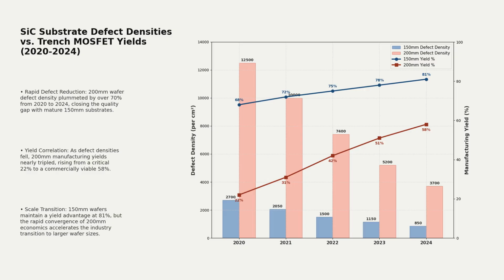These defects, primarily threading screw dislocations, compromise the physical structure of the wafer. During high aspect ratio reactive ion etching, these dislocations concentrate electric fields. This causes localized gate oxide breakdown at voltages up to 30% below rated capacity. Consequently, manufacturing yields for 200mm trench devices remain suppressed at 58%. This is far below the 80% threshold required for stable, low-cost commercial volume production. The physical limitations of crystal growth are directly restricting the supply of advanced power electronics.